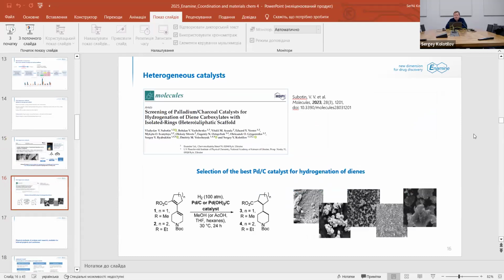Another example, it's a selection of the best palladium catalyst for hydrogenation of conjugated dienes. So the formulas of these dienes you can see on the slide. I will not take time to explain why it is important. But the problem was that dienes are not very well hydrogenated because of conjugation. And due to high conjugation energy, they usually require much more harsh conditions for hydrogenation compared to usual alkenes. So we found a series of palladium catalysts deposited on carbon, and we can carry out this reaction in very mild conditions compared to what we had before the beginning of the study.